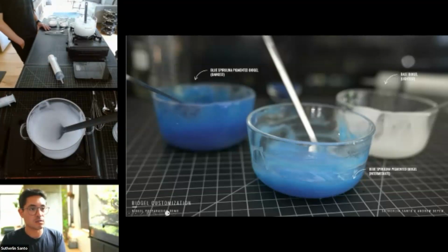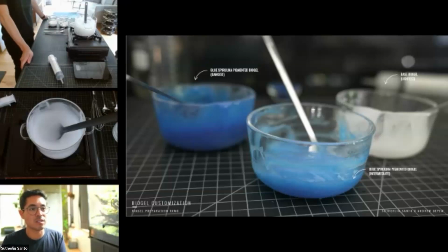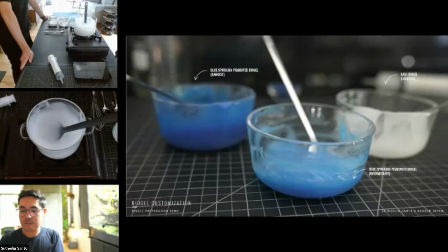to produce lighter tones. It is not advised to attempt to weigh out the spirulina in quantities that would produce the correct colors that you're looking for in these small values, just because this middle blue spirulina could require only 1 or 2 grams. I'm sorry, this middle light blue. And it is almost impossible to measure in those small amounts and reproduce it accurately. In larger quantities, where instead of 1 to 2 grams of spirulina, it might be like 5 grams of spirulina, that might be more realistic.